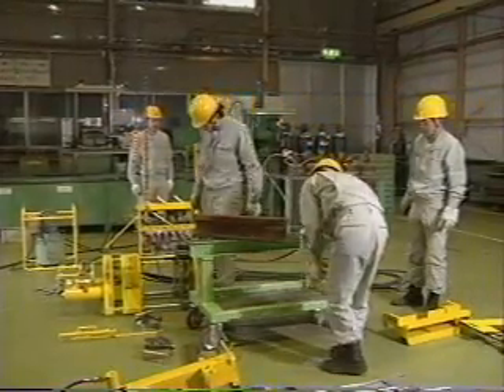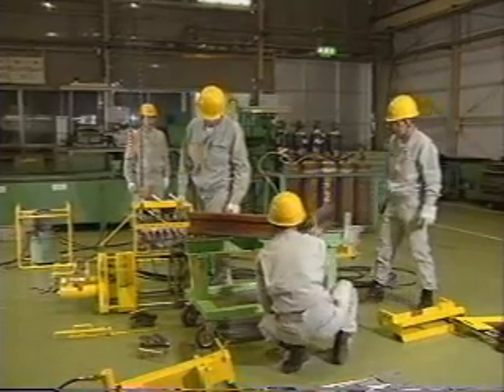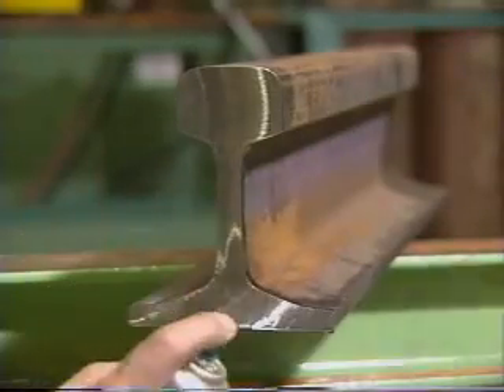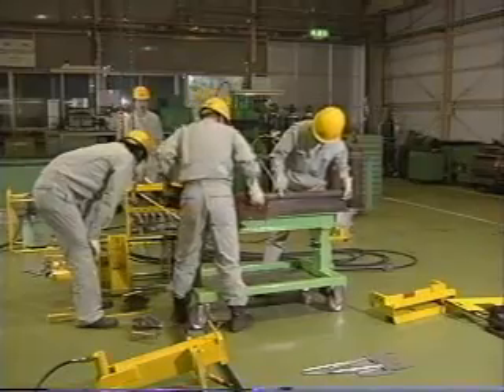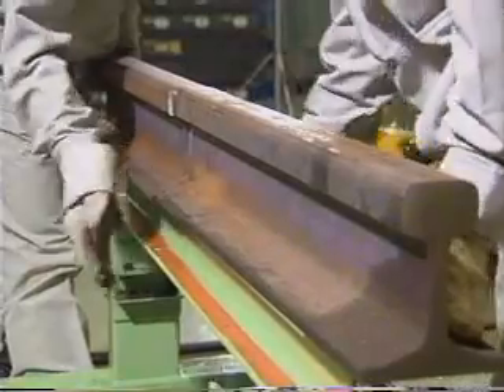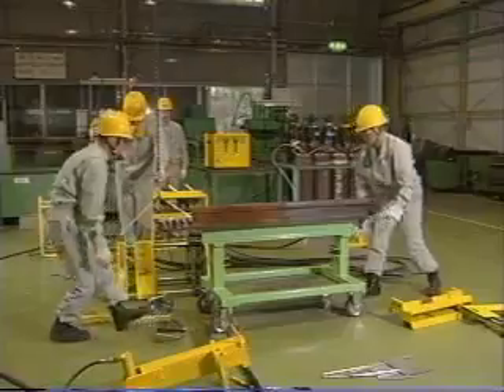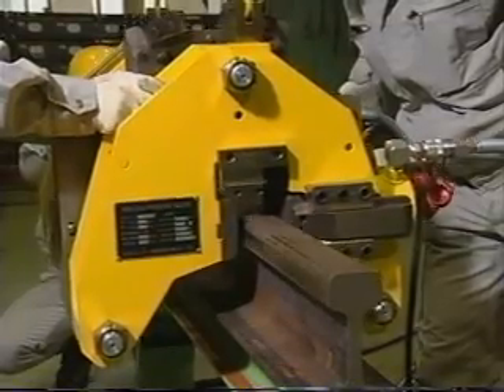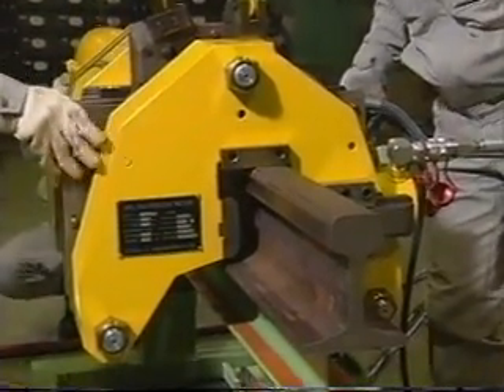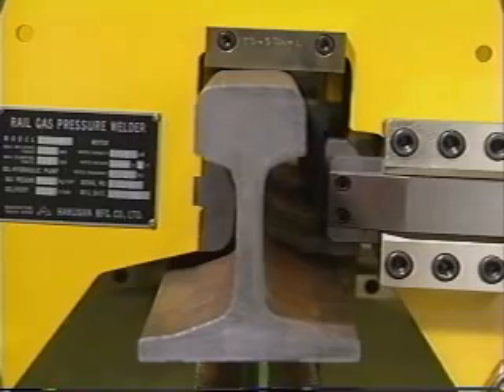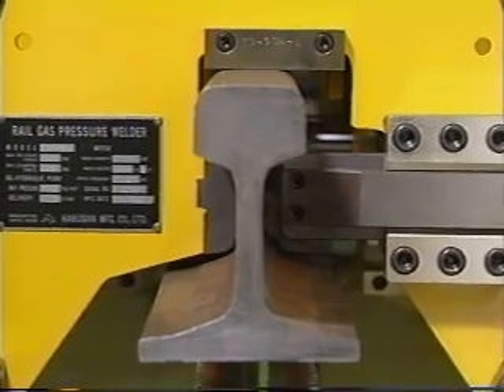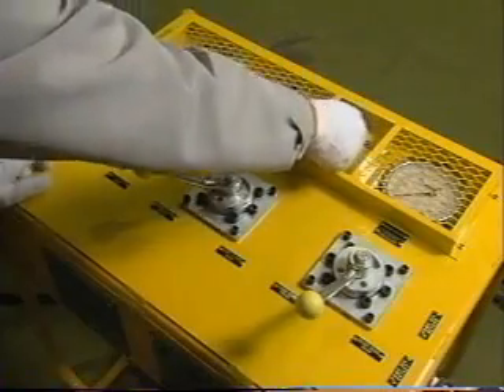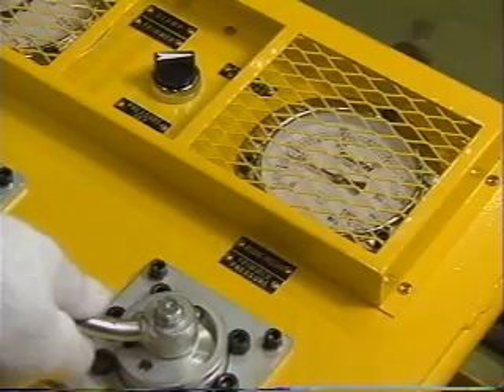Clean the end faces of both rails after each face is finished by grinding machines with cleaning liquid to completely remove impurities such as oil, dirt and iron powder. Then we butt both end faces. Set the gas pressure welding machine, clamp the rails to set the prescribed pressure welding amount, and then start pressurization.